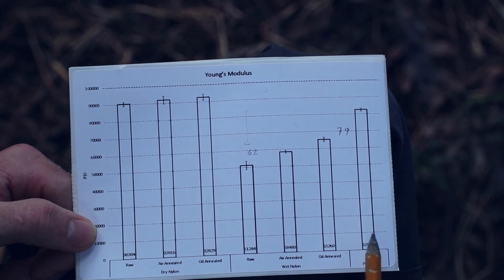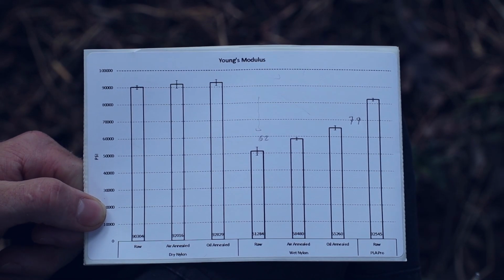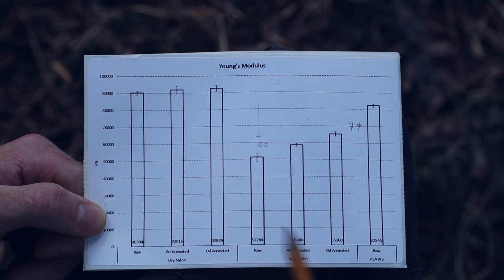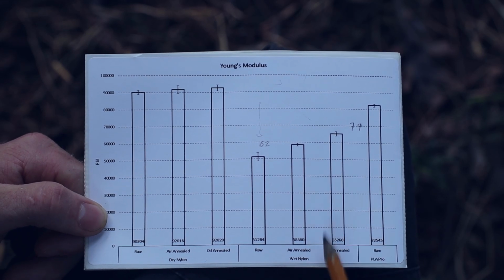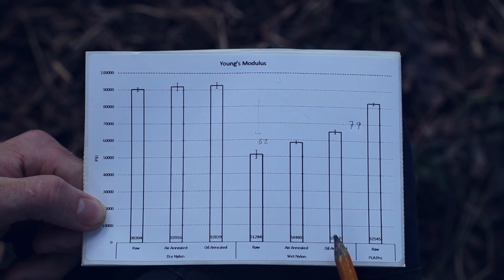Looking at the Young's modulus, we come to a similar conclusion as we did looking at ultimate tensile strength, and that is that, yes, the oil annealed nylon does increase the stiffness after moisture absorption.